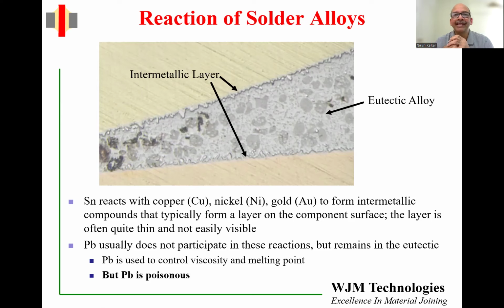So for example, if you take a tin-based solder, let's say a tin lead solder. When the solder alloy melts and you have the right flux and you remove the oxides from the surface, the tin will then react with the base components. The base components in soldering are typically copper, or they might have a nickel plating or a gold plating on it. And tin will react with all of them to form intermetallics. Oftentimes the intermetallics will form a thin layer on the surface. A lot of times the layer is so thin that it is very difficult to see. So you might feel that in this case there is no reaction product, but the reaction product is going to be there. It's just very, very thin.